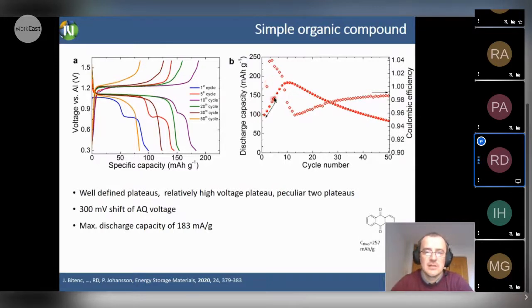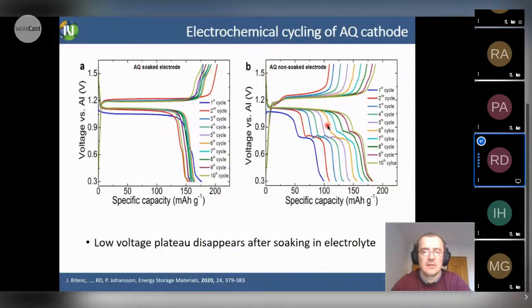And as you can see, the stability was pretty good for this starting experiment, but of course far away from something that can be used in some serious commercial application. And also the Coulombic efficiency stabilized around 98-99%. So we again used FTIR methodology, FTIR operando mode experiments, and we studied that, but we did also one